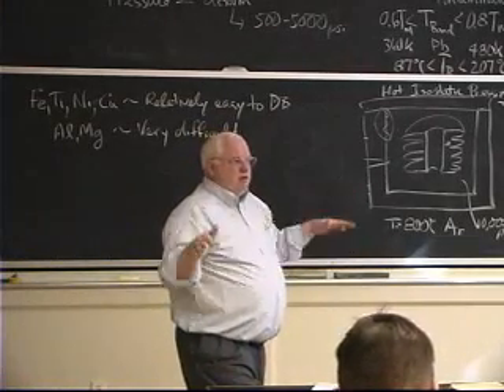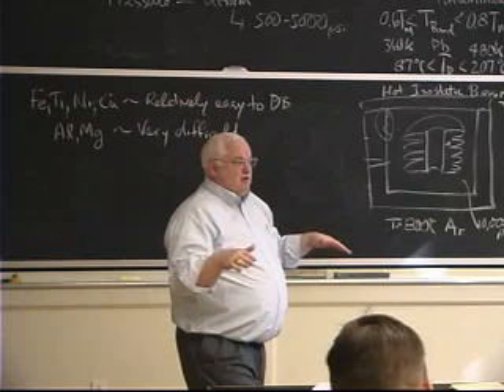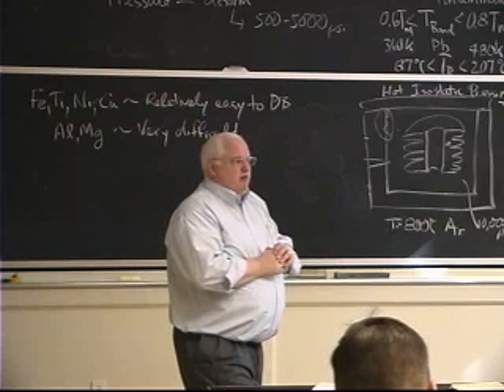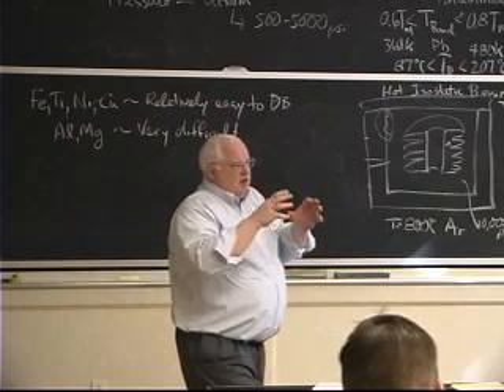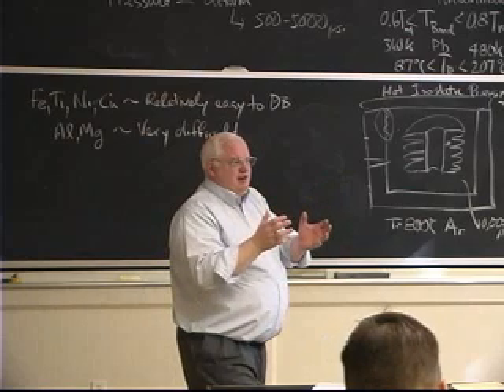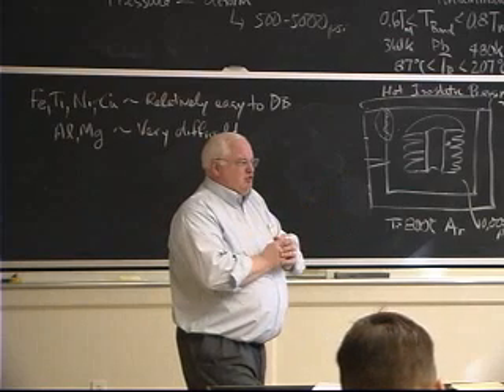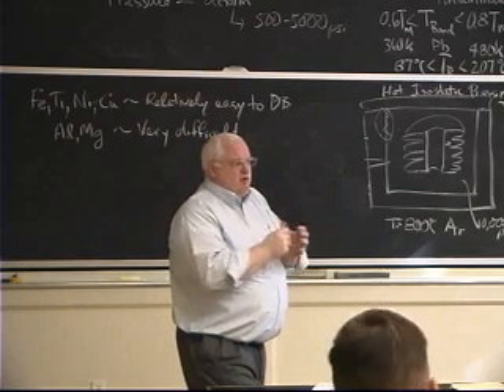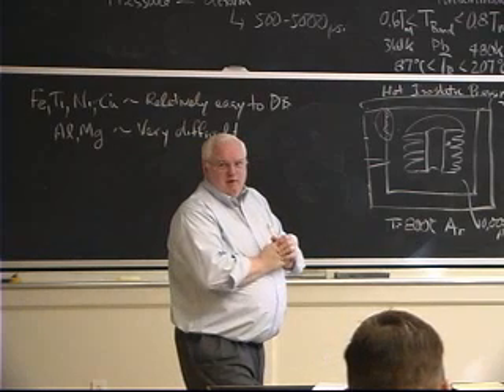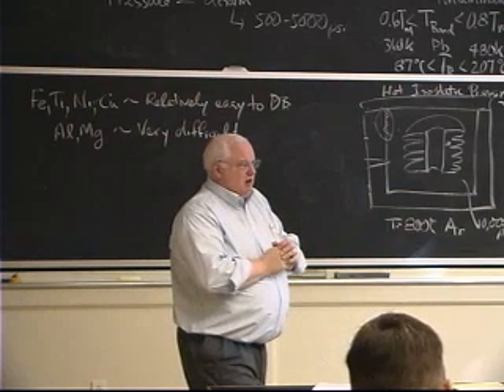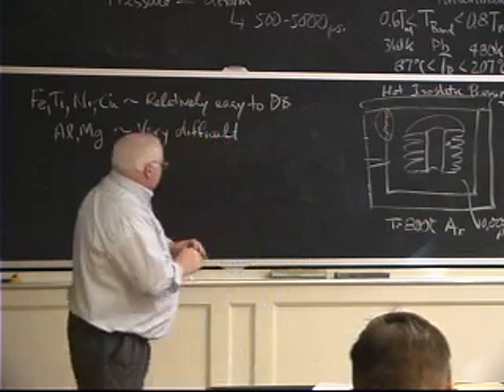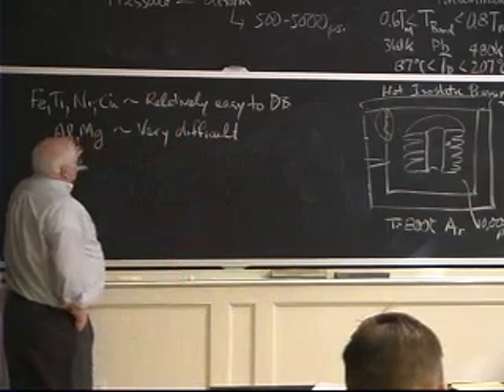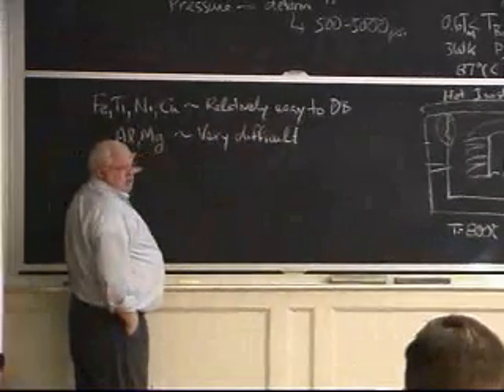You can go above the melting point. In fact, if you've ever seen aluminum melt in a fire, it actually sort of sags and it has its own aluminum oxide skin. The aluminum oxide still has strength and will actually support the liquid aluminum on the inside for a little while, when you first get melting. So these can't be diffusion bonded, or it's very difficult.